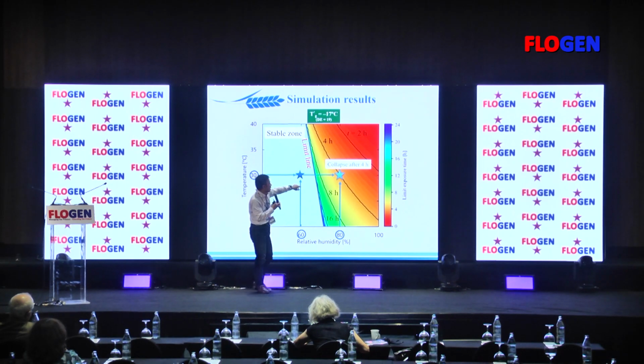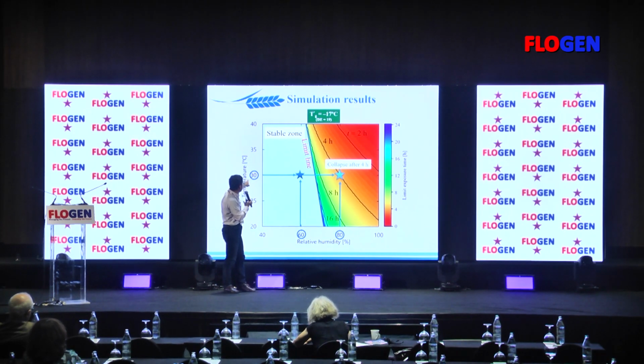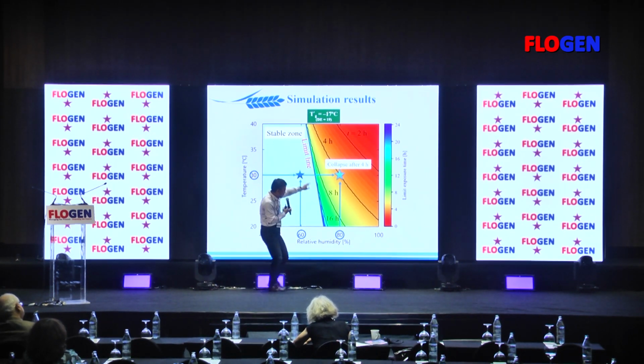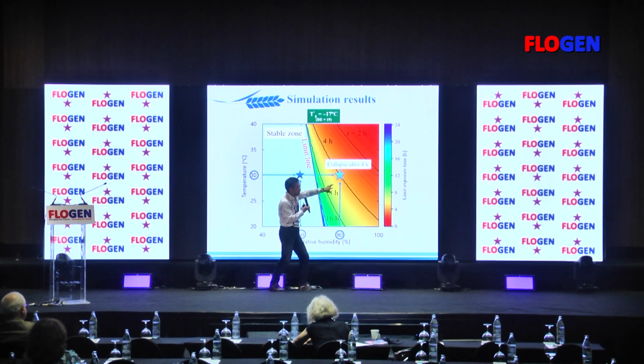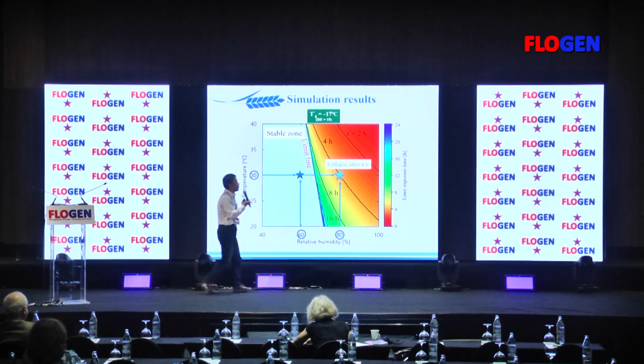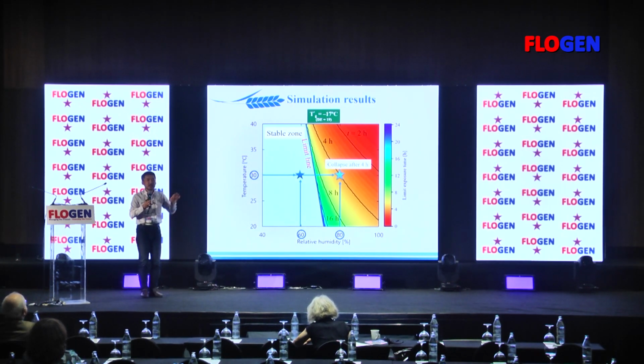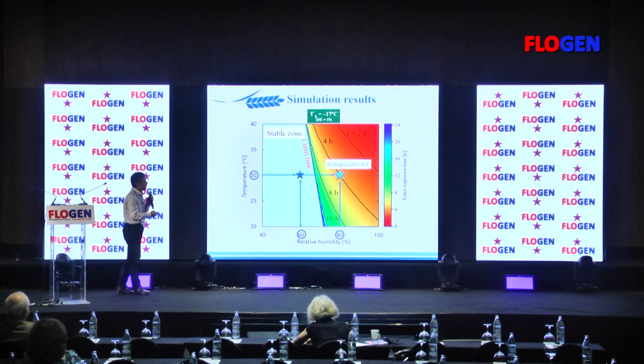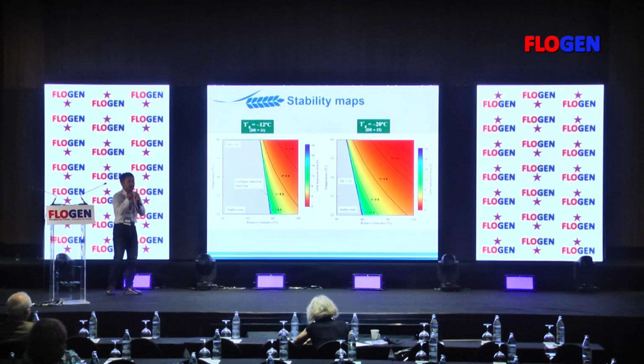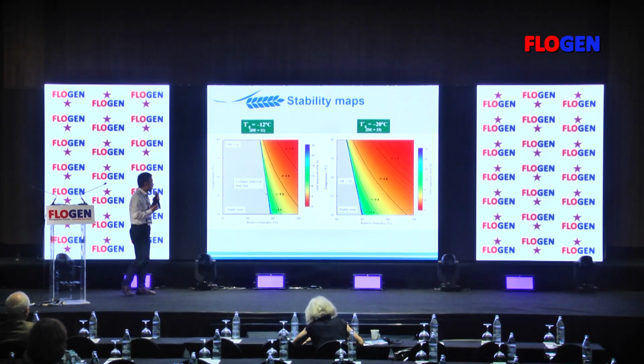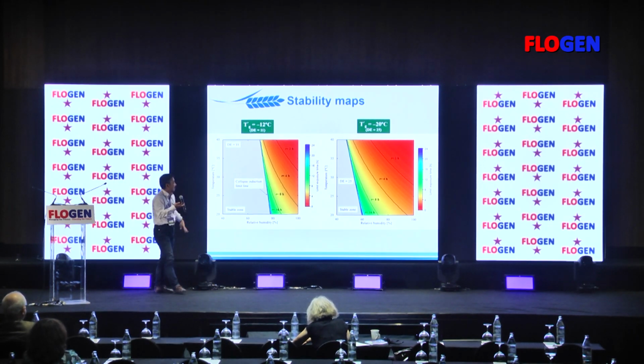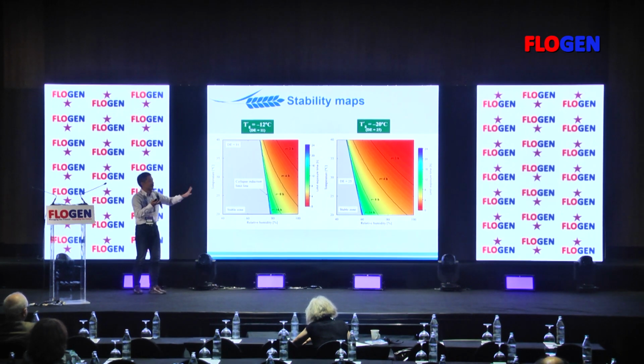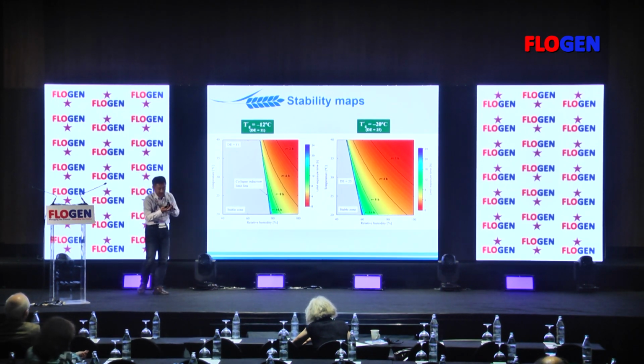Another important part is the kinetics. For example, we have a matrix with a certain glass transition temperature, and if we place this one at 30 degrees Celsius at the humidity 80%, it's extremely high. Then this estimation says after 4 hours, this matrix starts to collapse. Then this can be applied to another matrix with different glass transition temperature. If the glass transition temperature is higher, then the stable zone is wider, and also the kinetics is different from the previous one. And if we apply it to another matrix, then the result is different.